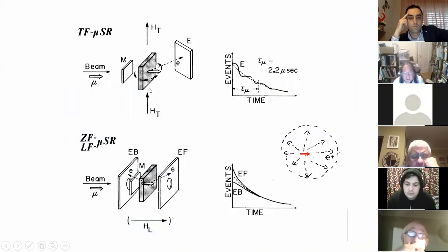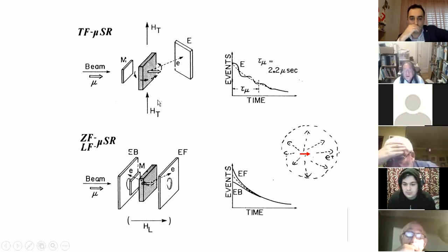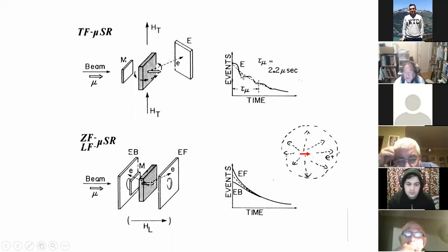But the method I would show you today requires applying an external magnetic field perpendicular to the spin direction. And then what happens is that this muon spin is precessing around this external magnetic field. And so if you have a counter here, for example, you will see the oscillation of muon spin as long as spin polarization is kept. And so from this oscillation, you can measure again how long the spin polarization is maintained or if it's destroyed, and if the internal magnetic field in the material is the same or different from the applied external magnetic field, and so on.